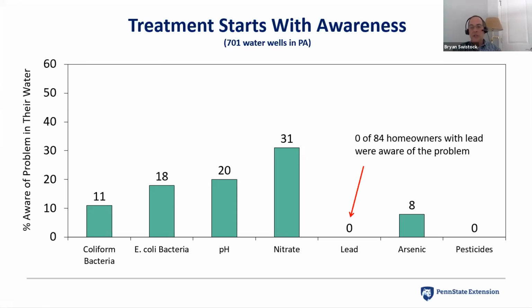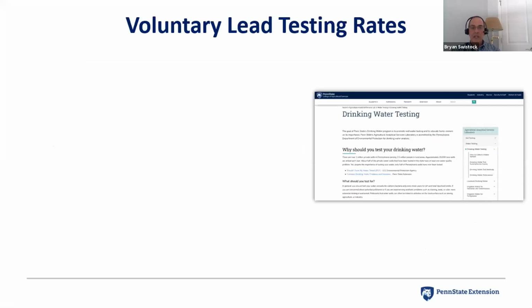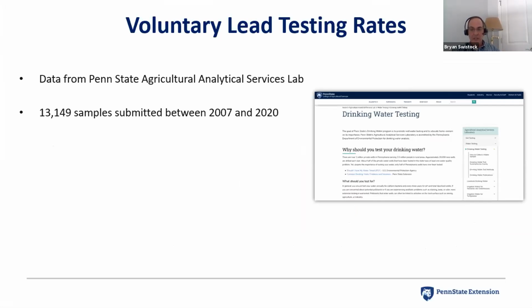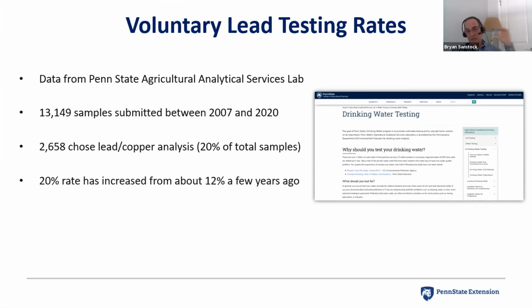Similarly, bacteria, there's more awareness because there's more testing of that problem as well. So the big hurdle to overcome with treatment of lead is, first of all, making people realize that they have a lead problem and getting them to test the water. And we see here in Pennsylvania, with our lab, the Ag Analytical Services Lab here at Penn State, over 13,000 samples since 2007. A little under 3,000 of those people chose to do lead and copper analysis, which is about 20% of all the samples. So these are people selecting to get their water tested, and they select what they want to have tested. And only about 20% select to do lead and copper analysis. And that's actually higher than it used to be. We found up until a few years ago, it was running closer to about 10 or 12%.